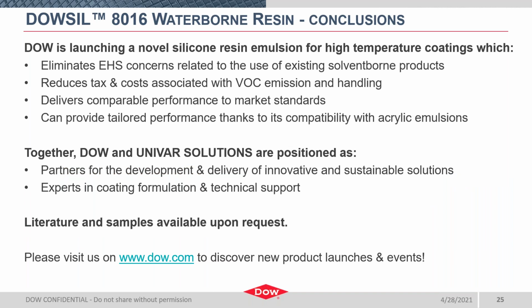Okay, I have reached the end of the data sharing for the webinar, but I do want to quickly wrap up by concluding a few take-home messages. The DOWSIL 8016 waterborne resin addresses a previously unmet market need for a silicone resin that is truly delivered in water-based form without solvent inclusion that can compete with the traditional solvent-based silicone resin performance. In addition to the excellent performance, 8016 eliminates EHS concerns inherent to solvent-based resins and allows for even lower VOC formulating.